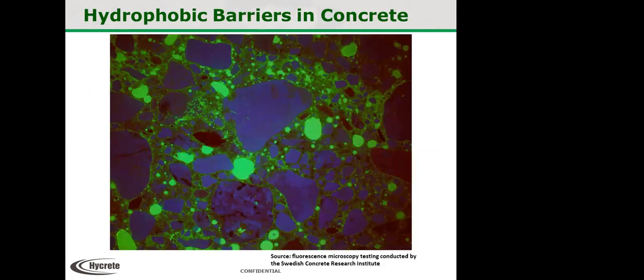Here's a picture of a concrete pore blown up. You can see here the green is the hydrophobic, and blue is basically the concrete around the pore. As you can see, the hydrophobic completely surrounds any of those pores, so the water is not going to go anywhere if it got in. If there's a wet area of that concrete, the water is not going to migrate to any part of it. And that works at all depths of that concrete, since it's mixed in integrally.